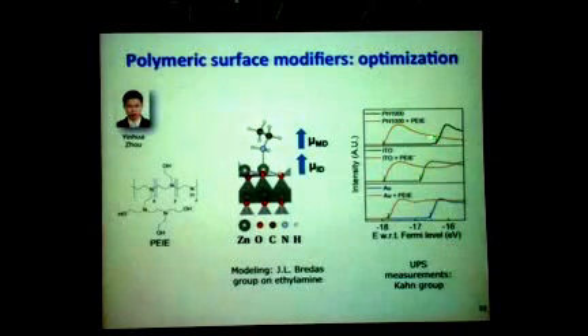It also works on a conducting polymer—pH 1000 is actually a PEDOT:PSS grade, high conductivity grade. You can again turn a conducting polymer into a low work function electrode, or you can use inert metals like gold, just dip it into a dilute solution like this, and you'll end up with a stable, low work function electrode.